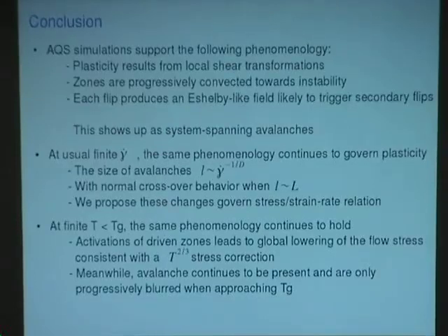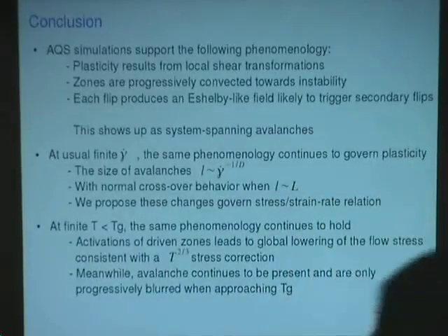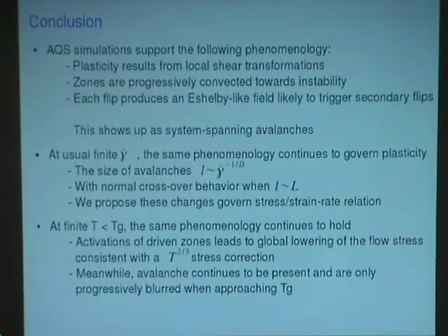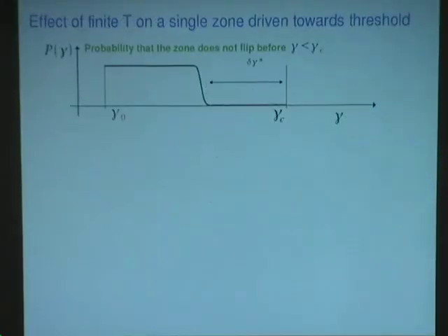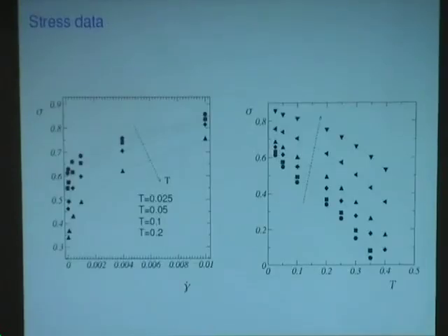Questions or comments? Mark? In terms of the last part of your talk, you seem to have a power law dependence of stress on strain rate. We've looked a lot at this issue in three-dimensional systems, and there's initially a logarithmic rate dependence, followed perhaps at very high strain rate by something that's more power law, and a very nearly linear drop with temperature. Can you say a little bit more about this?